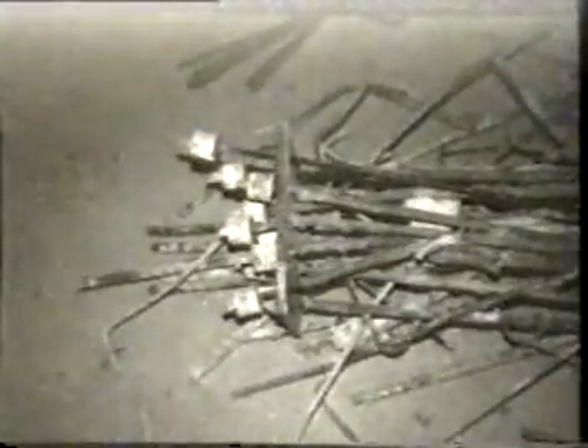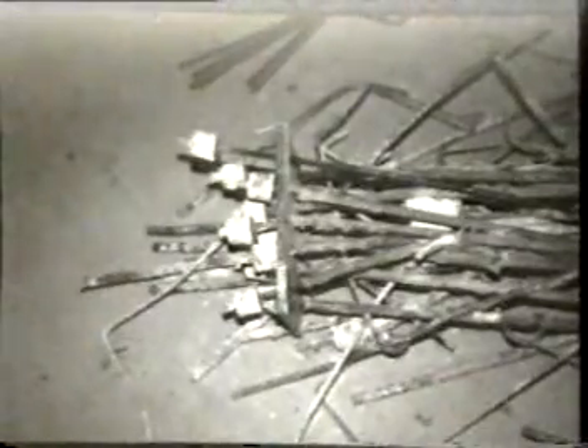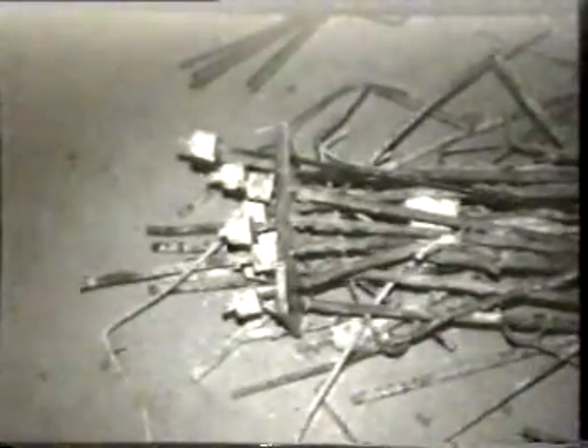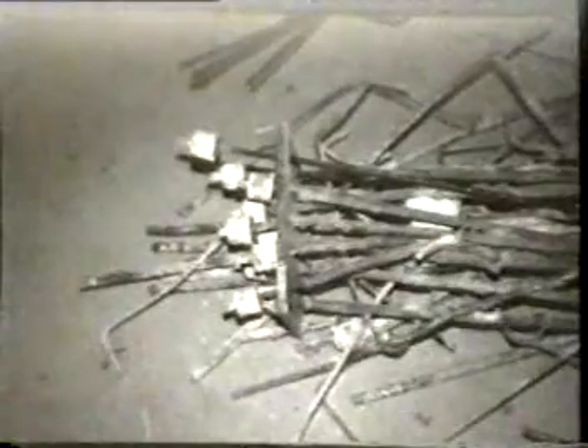Post-tension. There are a lot of post-tension structures out there, and if you're on the repair side of it, it's a great business. These are structures that are built with cables that are stretched with a lot of tension. There's a lot going wrong with these structures. Water's gotten into these systems and caused corrosion. And just to point out, there is a task group here at ICRI that's dealing with the issues associated with these types of problems, and they meet at 1:30 this afternoon. So if you're interested, I recommend that you attend and participate and just see what's going on in the task group.